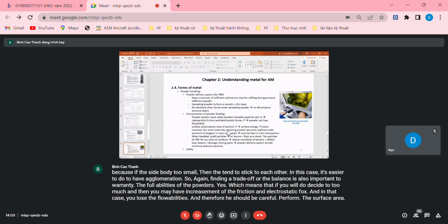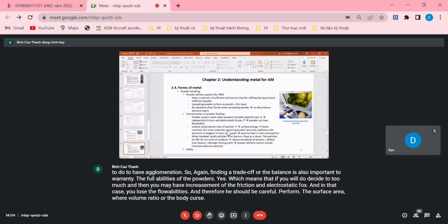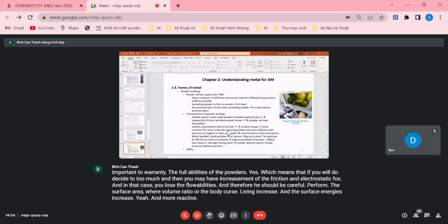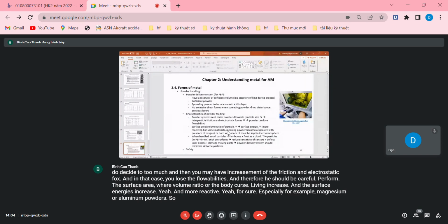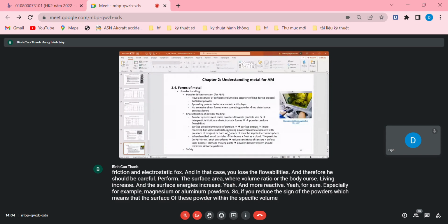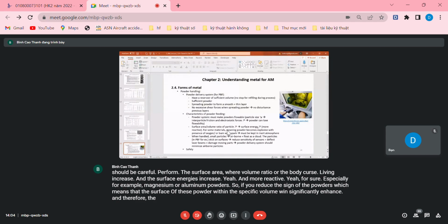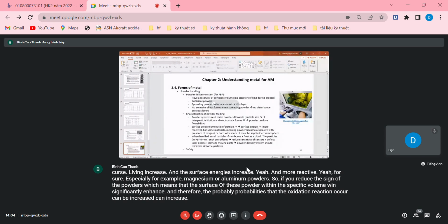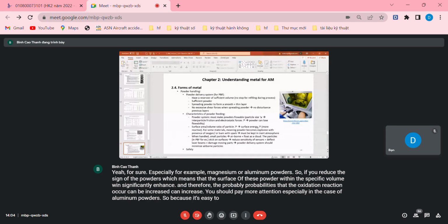The surface area per volume ratio of the particles, if it increases, the surface energy is increased, and the powder is more reactive. Especially for example, magnesium or aluminum powders. So if you reduce the size of the powders, the surface of these powders within a specific volume will significantly increase, and therefore the probability that the oxidation reaction occurs can be increased. You should pay more attention, especially in the case of aluminum powders, because it's easy to react with oxygen, or easy to be burned with electric discharge.